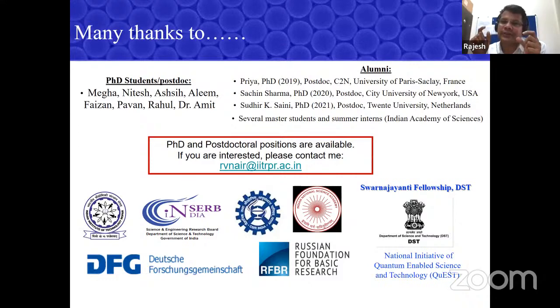So in a 2D photonic crystal, to measure the band gap, suppose I have a crystal and I need to measure in one direction, and then I need to measure the second direction. So what I do, I measure reflectivity from here, and I also measure reflectivity from here, and I see whether these reflectivity peaks overlap. That means if they overlap, the light at that wavelength cannot propagate whatever be the direction you launch it.